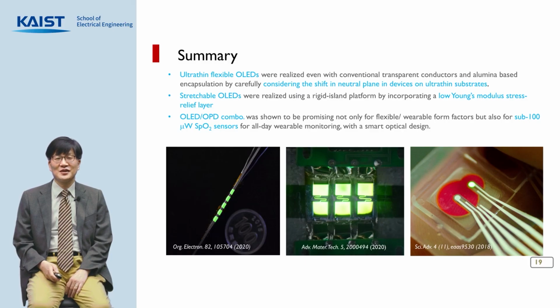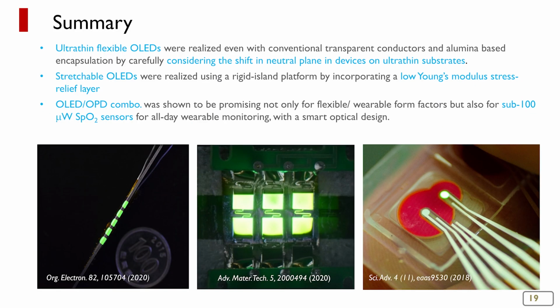Ultra-thin flexible OLEDs are realized even with conventional transparent conductors and alumina-based encapsulation by carefully considering the shift in the neutral plane in devices on ultra-thin substrates. Stretchable OLEDs were realized using a rigid island platform by incorporating a low Young's modulus stress relief layer. The OLED and OPD combination was shown to be promising not only for flexible wearable form factors, but also for a sub-100 microwatt SpO2 sensor for all-day wearable monitoring with a smart optical design.